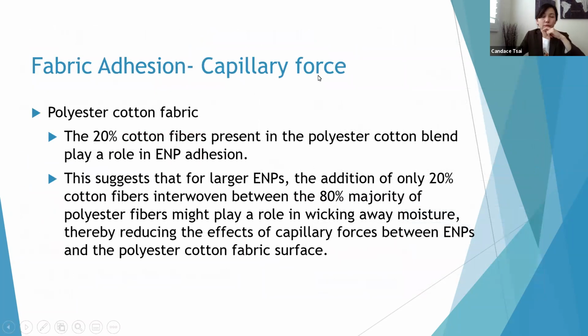The capillary force matters because the surface interaction was dominated by those two forces together, not just the van der Waals force but also the capillary force. For the cotton and polyester cotton, remember cotton fabric, you wear a cotton t-shirt.